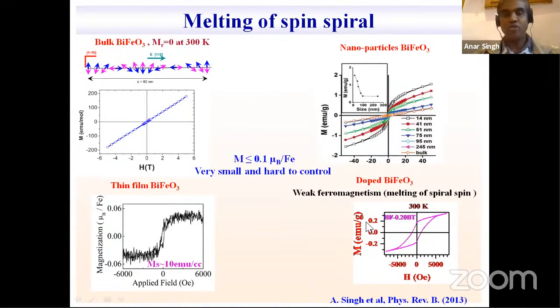And the third route is to make solid solutions of bismuth ferrite with other perovskite materials, or by some kind of doping at the A or B site of the perovskite structure. So we can also have some ferromagnetic component here. But in all cases, the ferromagnetic component is less than 0.1 mu B per Fe, and this is very small. Such a small magnetic moment cannot be controlled by electric voltage. So this is the challenge which we are facing in making devices of bismuth ferrite.